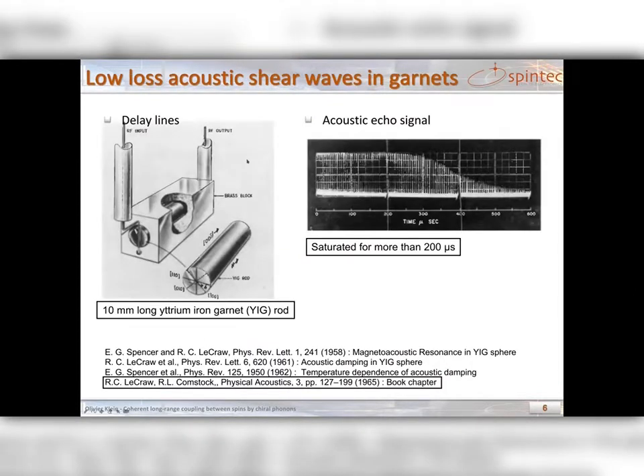So, one important ingredient, as I've shown earlier, is this acoustic damping. And I want to start by showing you an old experiment done in the 70s at Bell Lab on delay lines. Here you have a 10 mm long rod of yttrium iron garnet, that is called YIG, that is excited on one end by ferromagnetic resonance. And what is measured here is the acoustic echo signal. And what you can show here in this panel is that surprisingly, this echo signal survives for a very long time. And one can only see the decays after 200 microseconds.